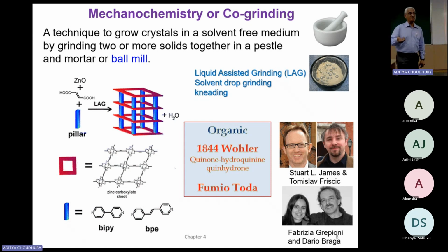But at that high temperature, people say that things can melt, and then crystallize. But again, you are continuing grinding. When you continue to grind, you are smashing all the crystals. What is happening in this case, when you grind them and leave it, you usually add a few drops of solvent. This is the mechanism, okay? When you add solvent and grind them, the reaction will happen in the solvent medium locally, even in a drop. That's where the reaction proceeds, and the solvent goes to the next mixture when you grind them, and then you get the product.